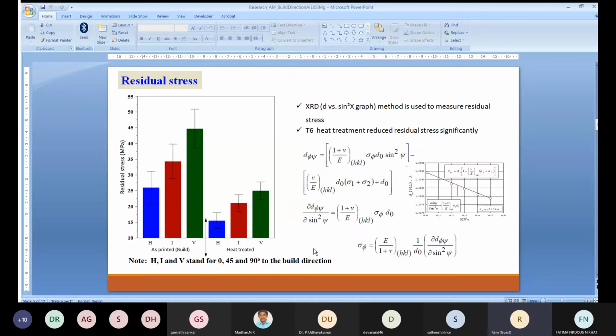We measured the residual stresses. Two important points you can see. One is the residual stress is reduced after heat treatment. Second point is the variation in the residual stresses also is reduced after heat treatment. And comparing different directions, the horizontal direction shows low residual stresses in the as-built and the heat-treated condition.